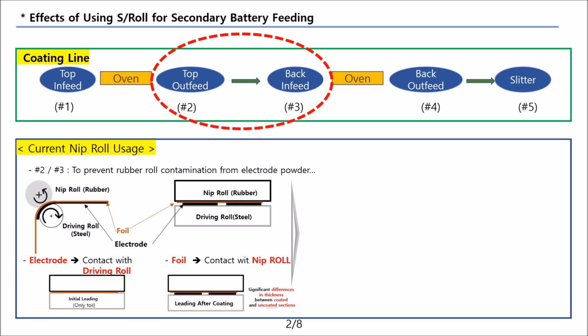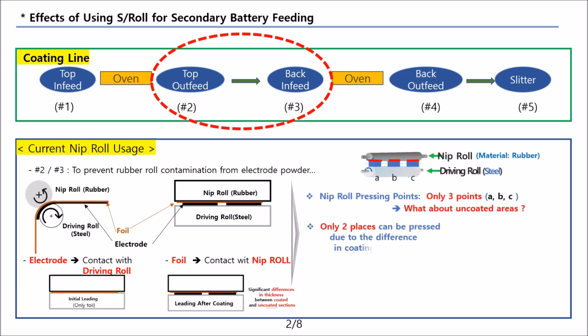The nip roll contacts the electrode at the three coated sections labeled A, B, and C, while there is no contact with the uncoated areas. Due to the difference in coating thickness, the nip roll makes contact with the three coated areas, but in reality, only two of these areas effectively exert pressing force. This condition can lead to material breakage and wrinkles in the uncoated sections.